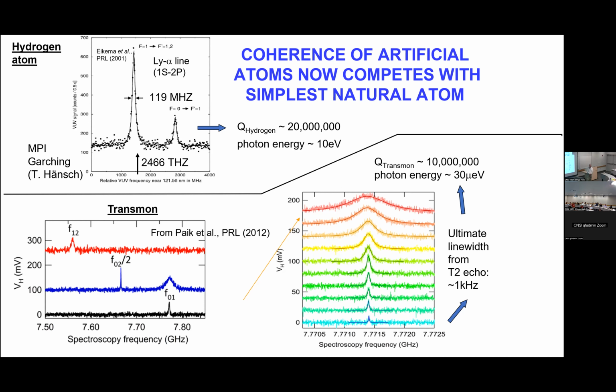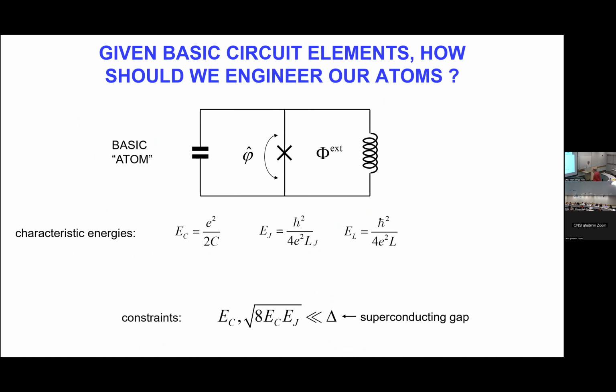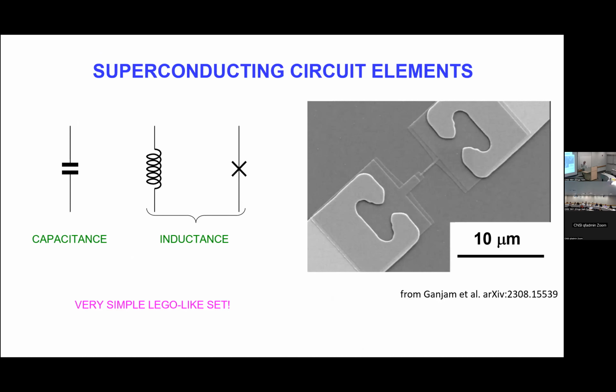But the tantalum, what role did tantalum play? Let's go back to this picture, because indeed I have to explain what the tantalum does. For the parts of the circuit where the tantalum is, you can subject the substrate and the metal to very aggressive cleaning. And it is believed that at least in the rest of the circuit, you have somewhat diminished the density of two-level systems.